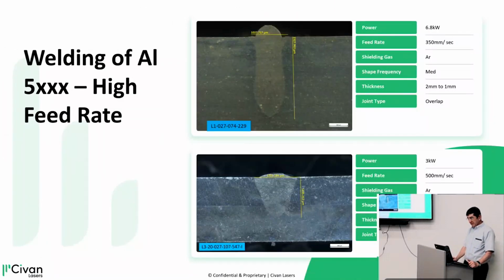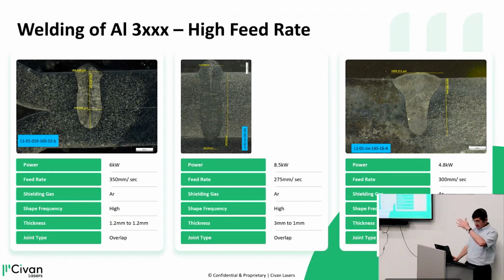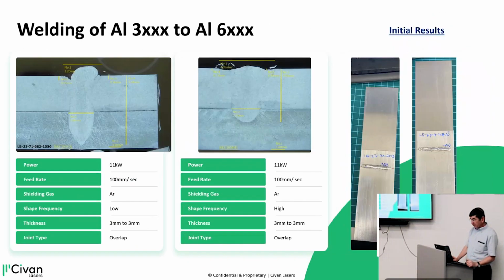These are a few examples. We can do it with different types of aluminum, by the way. Today, people do it in aluminum 3000, but aluminum 5000 or 6000 is stronger, so you can use thinner aluminum and get the structural strength. But it's very difficult to do because it's crack sensitive, but we are doing it. You can see here 500 millimeters per second. This is 30 meters per minute. And this is also aluminum 3000 in different configurations.